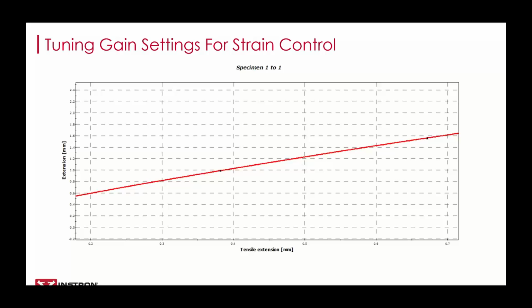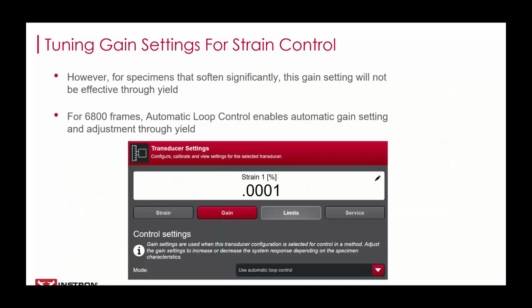Unfortunately, using a very small gain setting isn't the solution either. If you're using a small gain setting, that results in the frame making insufficient adjustments. The frame won't respond fast enough to keep close to the goal strain rate. When you look at the strain rate strain plot for a test with a gain setting that's too low, it'll seem like it's wandering past the goal and potentially going out of bounds before finding its way back again. So for repeatable, reliable, high temperature tests, neither of these options would be acceptable, which is why we don't recommend using a single gain setting for a strain control elevated temperature test.